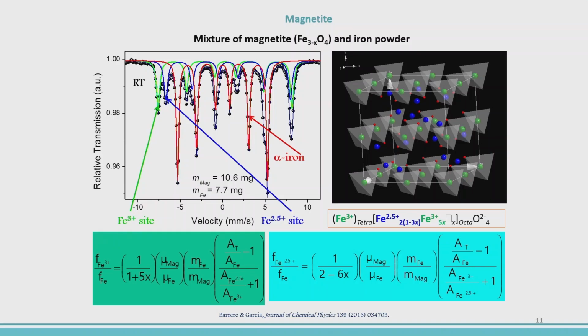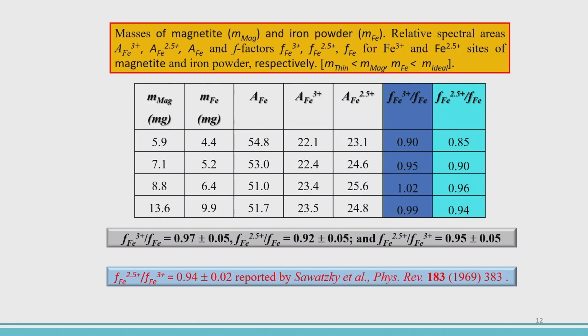And then we fit, and we show here some results. By using our method, we found that this relative recoilless factor is 0.97 for tetrahedral and 0.92 for octahedral, and the ratio between the two gives 0.95. This is very, very similar to a value reported earlier of 0.94 by using a very complex method. So we are proposing a direct and simple method to determine the relative factor for samples that exhibit two sites.